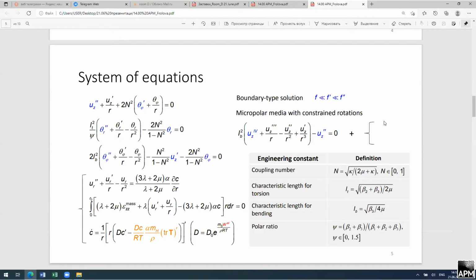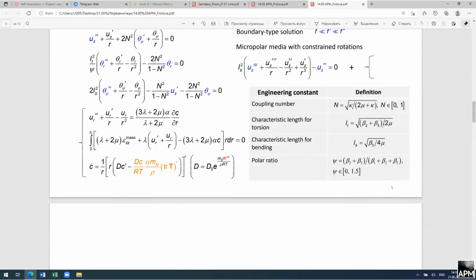And the same was done with micropolar media with constrained rotations, also only blue terms are present in equations. And here, instead of non-classical material constants, we use engineering constants, namely coupling number, characteristic length for torsion and for bending, and polar ratio. When coupling number is equal to 1, we deal with material with constant micropolar media with constant rotation. And values of characteristic lengths define the thickness of the area where the couple stress is active.